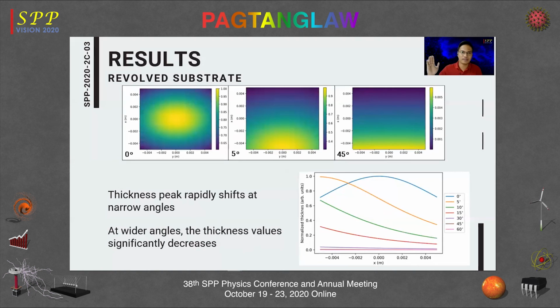And as you increase the angle further, the values of the thickness profile decrease by up to 2 orders of magnitude. Okay, so at wider angles, the thickness value significantly decreases, as you can also see in these line scans for the thickness profiles.